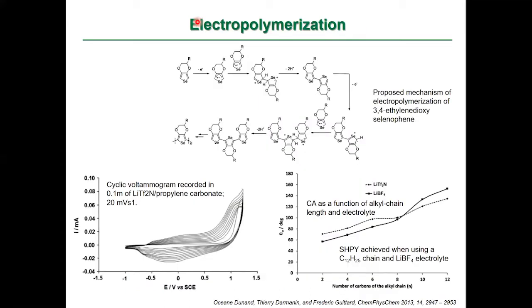So another method is well known as electropolymerization of conducting polymers. This is a proposed scheme of electropolymerization of 3,4-ethylenedioxyselenophene, and the electropolymerization is achieved through repeated cyclic voltammetry. You can see that the superhydrophobicity varied with the chain length when they used a